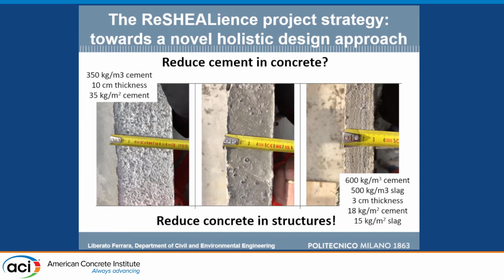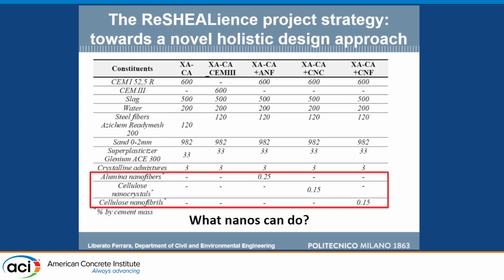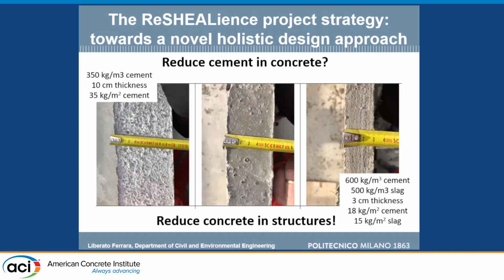This is to show the importance of the matrix. If you look at the dosage, you look at the mix design here. You say you have 600 kilos per cubic meter of cement. This mix is not sustainable. But look here, 10 centimeter thick with 350 kilos, you use 35 kilos per square meter of wall. In our case, with 3 centimeter thickness, you just use 18 kilos of cement per square meter of wall. So let's look at the functional unit and not at the unit volume of material or unit weight.